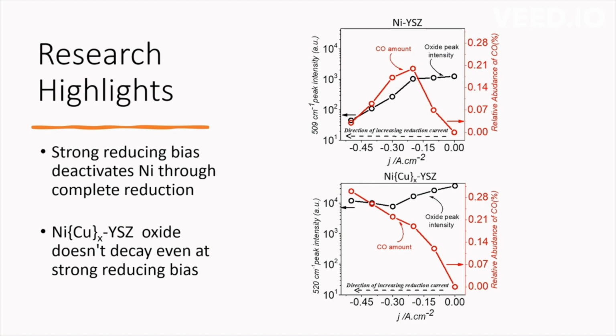CO2 electrolysis. On the other hand, in case of nickel copper, it maintains the oxide and carries out the CO2 electrolysis even at higher reducing bias. As we can see here, the CO signal increases with applying negative current density. So from this we can say the oxide is required to carry out the CO2 electrolysis. And by using temperature programmed activity study and theoretical study, we found that doping of the copper in the nickel oxide lattice significantly improves the bond strength of the nickel-oxygen-nickel bond, which helps it to remain intact even under strong reducing bias. Now up to here we understand that oxide is required.